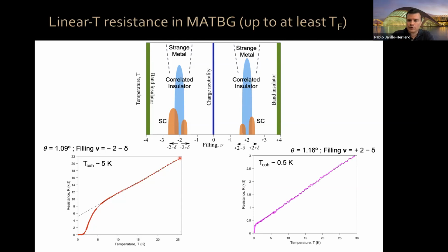Now, if you choose a doping and a sample, this is a 1.16 degree sample, the doping at +2 minus delta, very close to the tiny dome that we have here, you can see that superconductivity occurs only at extremely low temperatures, and then once you get out of superconductivity, you have this very linear behavior, again all the way to above the Fermi temperature, with the same slope, pretty much to zero. In this case, down to 0.5 Kelvin.